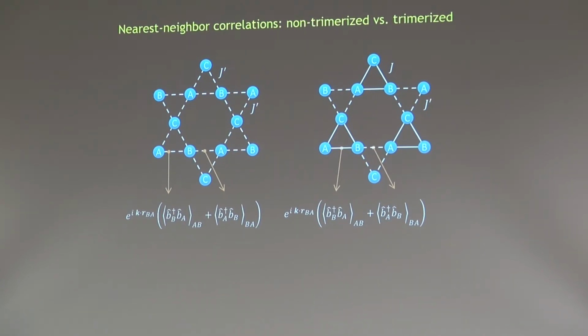So if I look at the diffraction of the atoms in momentum space, and I look along one particular axis, then I will see signatures of nearest neighbor coherences. And in the image, if I look at the modulation along this direction, I'll see signatures of the coherence between these sites and the coherence between these sites sort of overlaid on one another.